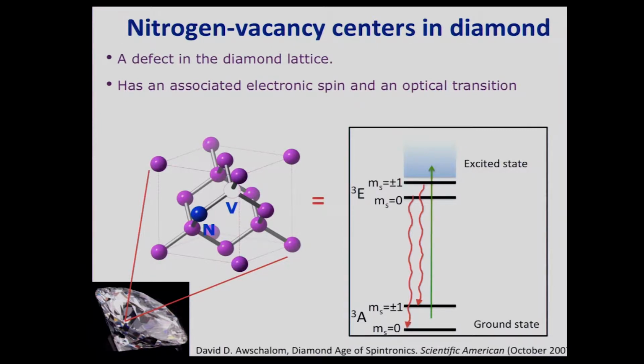And so, for instance, if you put a magnet in a magnetic field, it will precess, and it will do so at a rate that tells you something about the strength of the magnetic field. And that's what ultimately gives us our sensing abilities. And I already mentioned that this atomic-like system exhibits quantum properties, meaning that it retains quantum behavior in ambient conditions up to on the timescale of milliseconds, which is really quite remarkable for a solid-state quantum system.